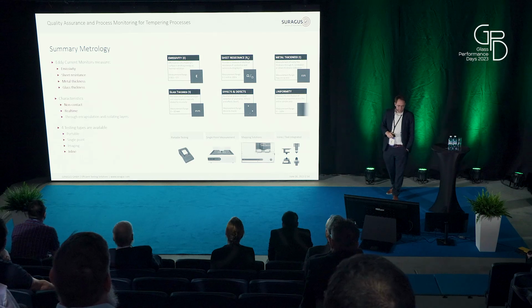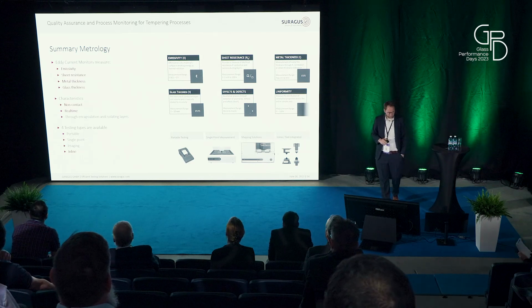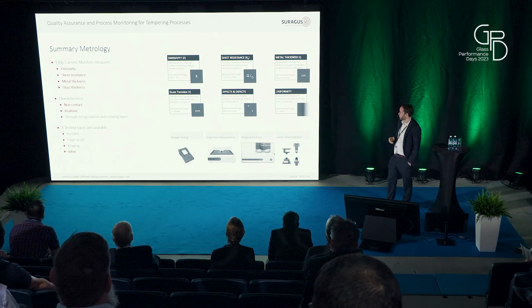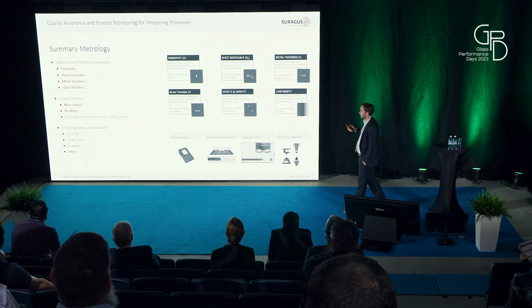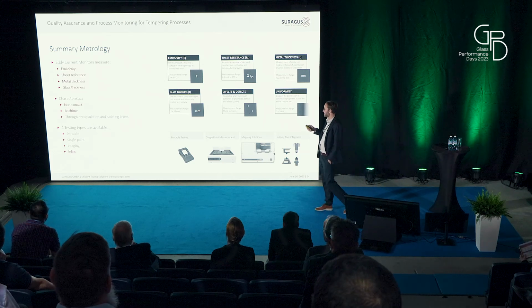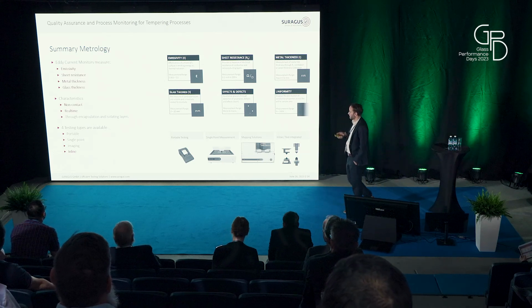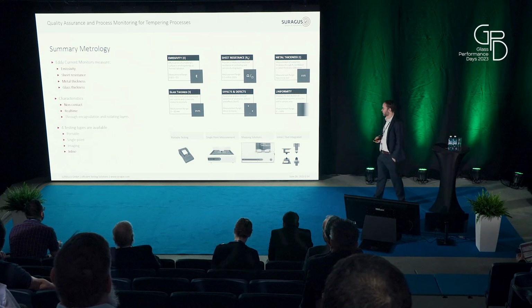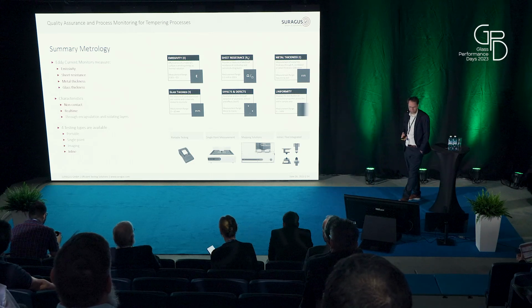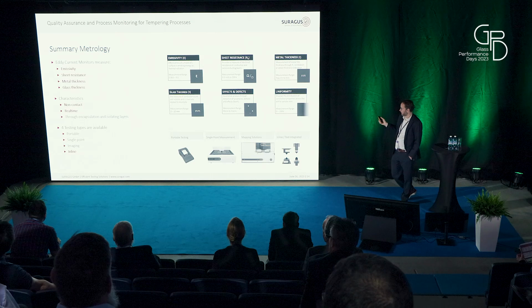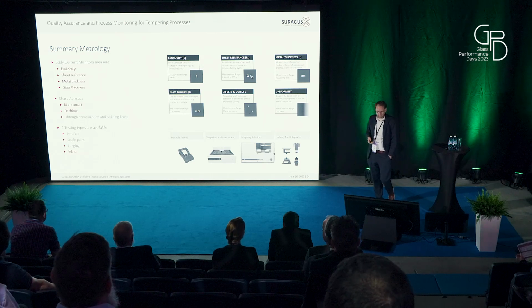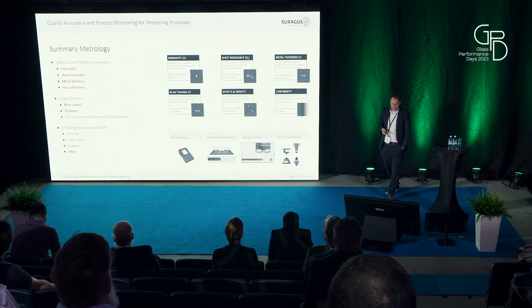Last slide, this metrology summary. Here I introduced eddy current monitors, which are able to measure the emissivity, the sheet resistance, and metal layer thickness. And it's a non-contact, very fast measurement, which also measures through the encapsulation. And there are different testing setups available. Portable and inline are the most relevant ones here.